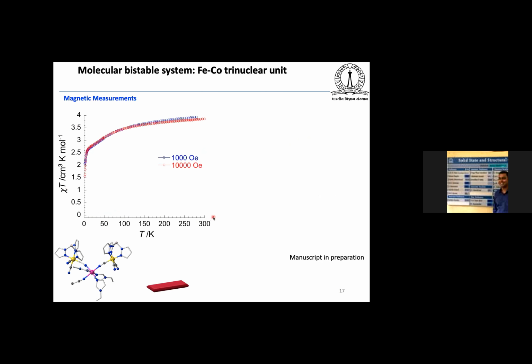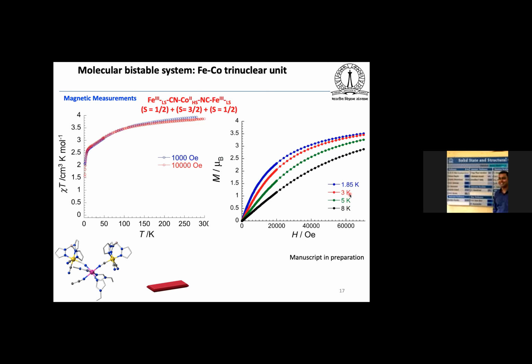And then when you measure the magnetic property of this trinuclear unit, you can see that the system is almost paramagnetic, and there is no electron transfer taking place when you cool down the system from 300 Kelvin to the low temperature up to 1.9 Kelvin. And you can see the chi T value matches well to approximately 3.6. That is a combination of iron 3 low spin and cobalt 2 high spin and iron 3 low spin systems. And you can also see at low temperature it is also matching with the iron 3 low spin, that is S equal to half system, and cobalt 2 is S equal to 3 half, and iron 3 is also S equal to half. They are connected in an antiferromagnetic fashion.